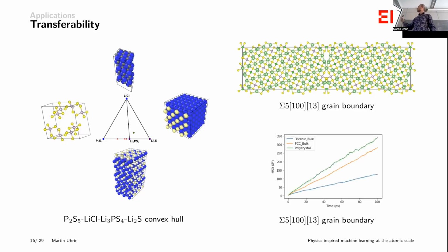And what you find, surprisingly, and these aren't very well labeled, but the orange is the original data, if you like, and this green one is the data from the run with the grain boundary in it. So actually, the conductivity in this case, which would be related to the slope of this graph, is higher, which is kind of weird. So you've got this grain boundary, which I might naively assume that when my lithium reaches it, it's going to have a harder time crossing.